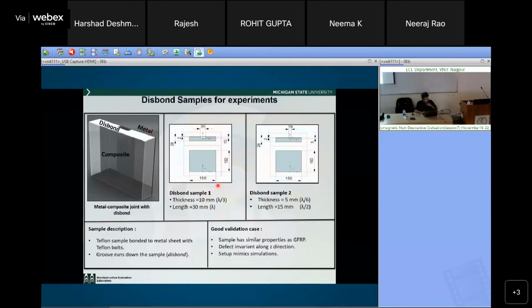So I think I showed a slide in the beginning comparing far field and near field measurements of the same 1 millimeter, 2 millimeter, and 4 millimeter holes. And the frequency was much lower than what you are talking about. Even at that low frequency, we were able to detect them using near field measurement. Near field measurements have no resolution limitation, right? Because it's more inductive and capacitive coupling. You're looking at the S21 parameters. So it could be just noise, or I need to look at the signal to determine what the problem is. Okay, maybe because of the noise. But in principle, it should be detectable at near field.